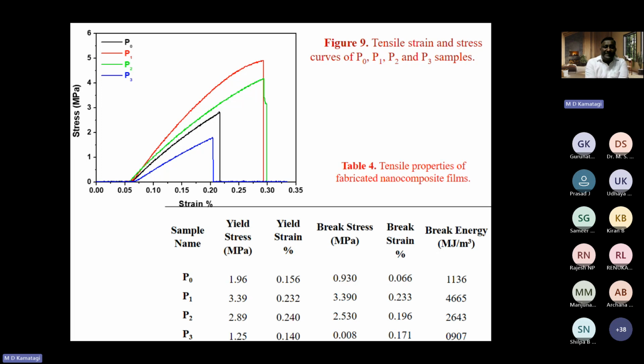Then what we noticed is we measured the stress after straining it. What we noticed is the P2 sample. Here we have tabulated the yield stress, yield strain, break stress, and break strain. What we have noticed is the PMMA has got lower stress. It can hold lower stress as well as lower strain. Whereas the P2 sample, the one which is doped with 3% of ZrO2,